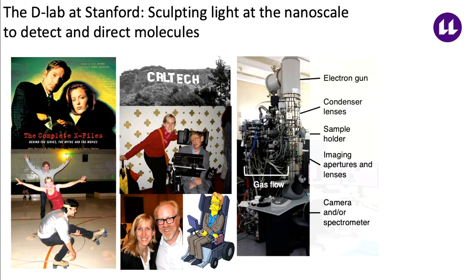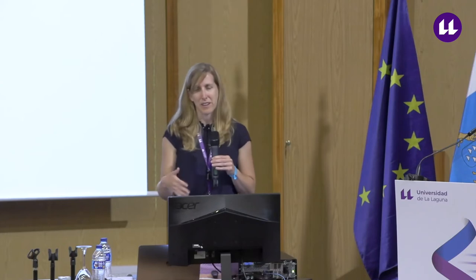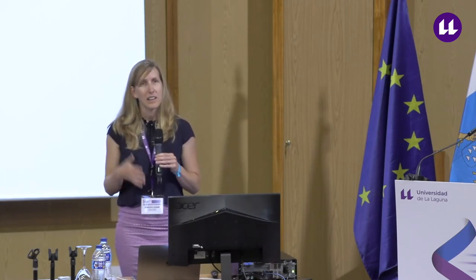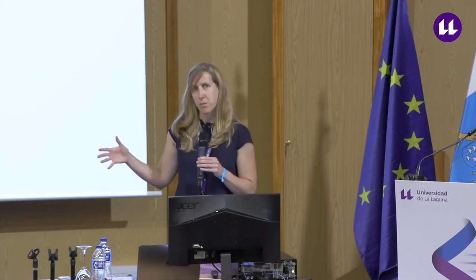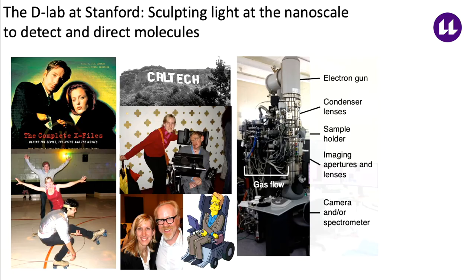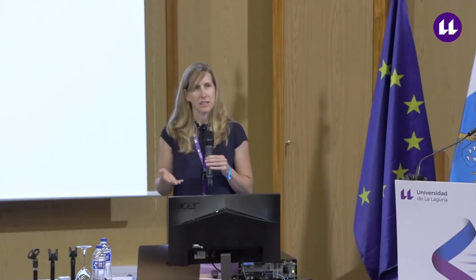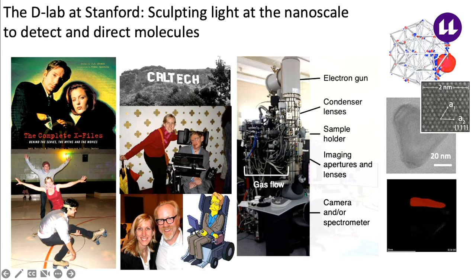Part of our work in my abstract, which I won't be presenting on today, is how we can make movies of molecular interactions. I love this work because it's very artistic but also addresses critical energy challenges — developing catalysts engineered at the atomic scale to enable high yield and product-selective photocatalysis. We've tried to link reactor-scale properties with the atomic-scale structure of these catalysts. To get atomic-scale insight, we use in-situ transmission electron microscopy. At Stanford, you can see our Titan environmental TEM, which unlike most TEMs that operate under vacuum, can operate under reactive gaseous conditions and in liquid environments.